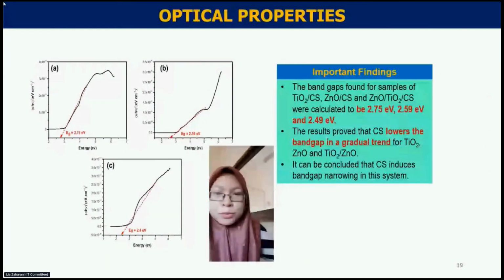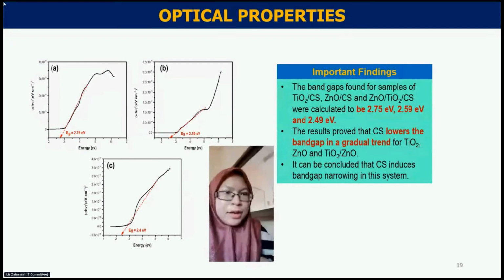In order to study the light sensitivity of this catalyst, the UV-DRS spectral analysis has been carried out. It shows that the band gap found for all the samples was calculated to be in the range of 2.75 to 2.49. This result proved that chitosan has lowered the band gap in a gradual trend for the titanium oxide and zinc oxide. It can be concluded that the chitosan induced a band gap narrowing in this system, which allows the prepared composite to be used for the photocatalytic removal of methylene blue dye under visible irradiation, to generate more electron-hole pairs and give maximum visible light harvesting.